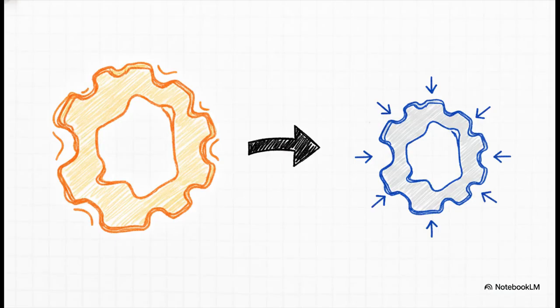And hey, if you're taking the leap and scaling up from a 3D printed prototype to full-blown injection molding, you absolutely cannot forget about material shrinkage. All thermoplastics shrink as they cool down from a molten state to room temperature. Now, ABS is quite stable. It shrinks about 0.5%. But something like polypropylene, that can shrink up to 2.5%, which is huge. That means the physical steel mold must actually be cut slightly oversized by the toolmaker to compensate. If not, your finished parts will be undersized and literally nothing will fit together.